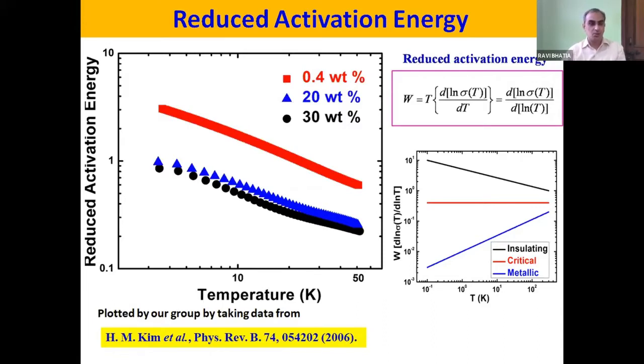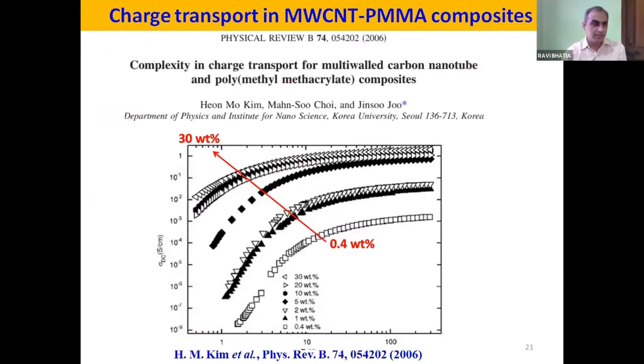questionable. The true picture from the addition of multi-wall carbon nanotubes into the composite should appear. It should reflect that CNTs are being added. But here again, the problem is, I believe that the aspect ratio of the material has been very low, or probably homogeneous distribution is not attained, or there could be defects in the carbon nanotubes which have been used to prepare these samples. So these two things clearly give a motivation that one should try to reassess the results obtained in this work.